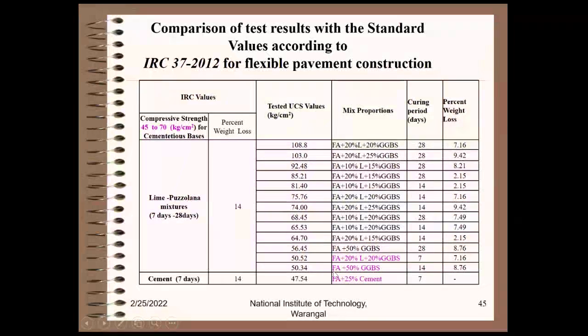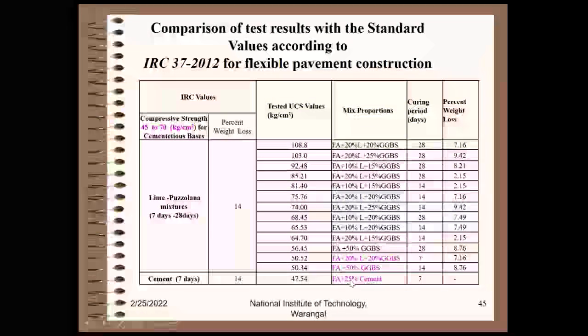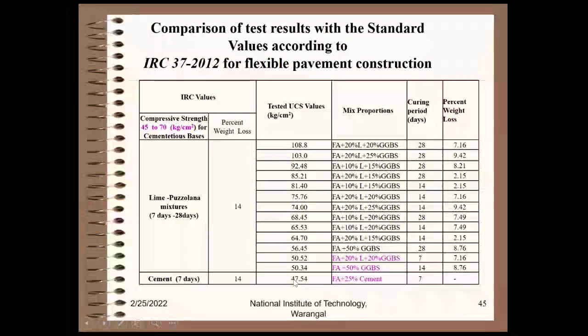Interestingly, you see, fly ash and GGBS alone also is able to give the strength, sufficient strength. Okay, cement even not added, lime not added also is becoming strong, because GGBS by itself is having lime content sufficiently. Even 25% cement is not able to do the job what this fly ash and GGBS could do. You see, this is a beautiful observation.